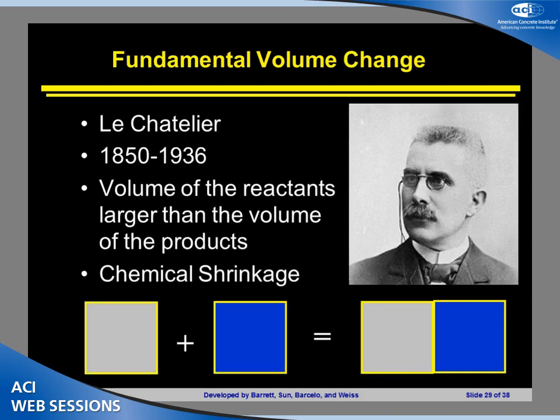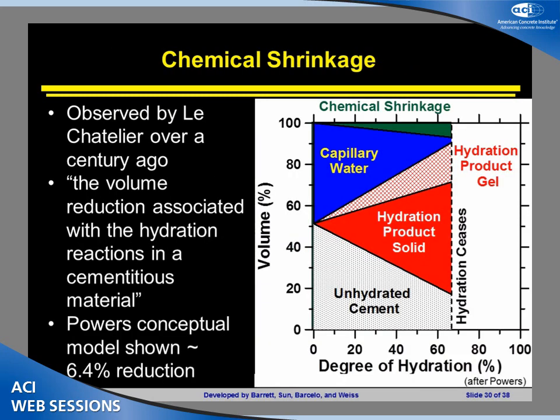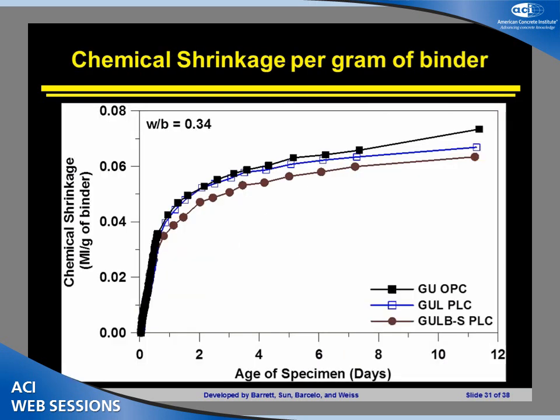So the chemical shrinkage, to really talk a little bit about this, chemical shrinkage is just a volume reduction that's associated with reaction. You start out with 1 volume of cement, 1 volume of water, and you end up with something like 1.86 total volumes when the whole system reacts. This has been observed and has been around for a long time, but I just want to point out here that if we look at the chemical shrinkage by binder, this is by clinker and ground limestone, we see very similar amounts of chemical shrinkage, very similar amounts of reactivity during the first week, and then we see the OPC maybe slightly higher again.